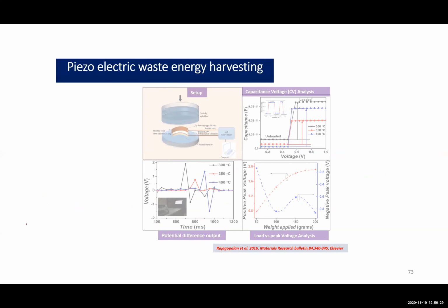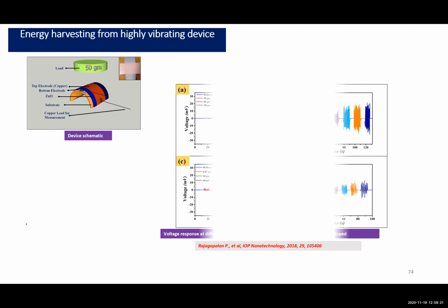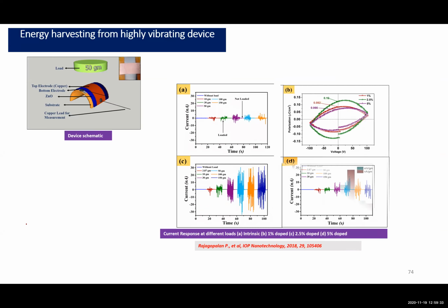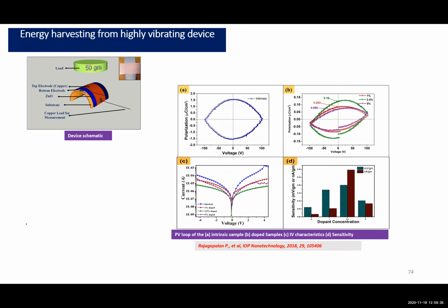As far as piezoelectric is concerned, one important aspect I would like to mention is that the commercially available piezoelectric has lead in it, which is harmful to the environment. So normally people are not interested in using it. In fact, it is not biodegradable either. In our lab, we have developed a biodegradable piezoelectric structure using a zinc oxide based system, making it at par with the conventional one.